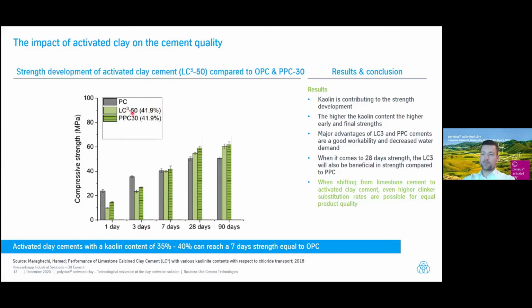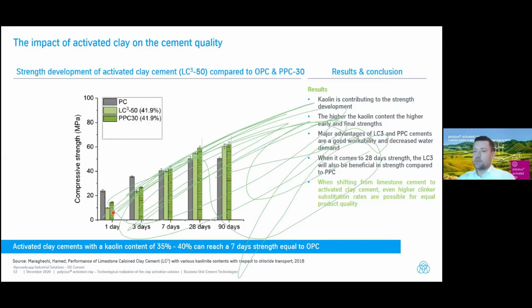So you have this composition, which means that there is 50% of clinker, 30% of activated clay, 15% of limestone, and 5% of gypsum. This is this one here, the green one. And then there is another one, which is the PPC30, also produced with 40% kaolinite content in the raw clay. And the results you can see here. So in general, what we see is that the performance of LC350 and PPC30 are more or less the same. Yeah? So the PPC is a bit better because the clinker content is higher, but in general, it's the same behavior, more or less.